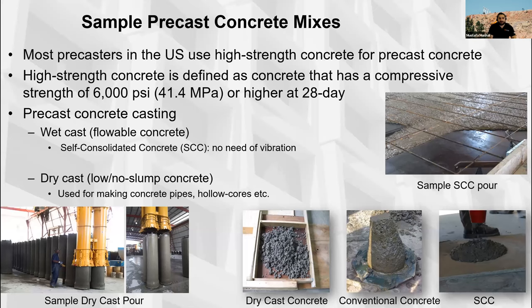The dry casting, also known as low or no slump concrete, is mostly used for concrete pipes on hollow core. Basically, there's no slump. This mix is very, very dense. And you see the difference in the photos shown below between conventional concrete, SCC, and dry cast.